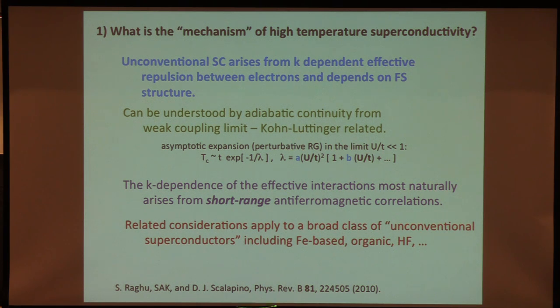And so with this sort of analysis, one can at least rationalize the nature of the unconventional superconductivity that's seen not only in the Cuprates, but in a variety of other things, just by looking at what momentum you think the biggest repulsions are, that comes from the magnetism, and what's the structure of the Fermi surface. From that you can make some inferences about the symmetries and character of the superconducting state, which at least more or less seem to be correct.